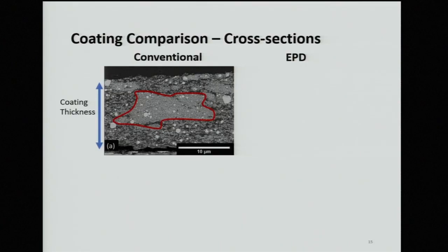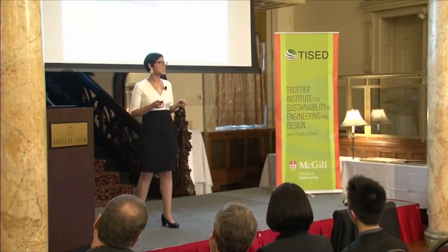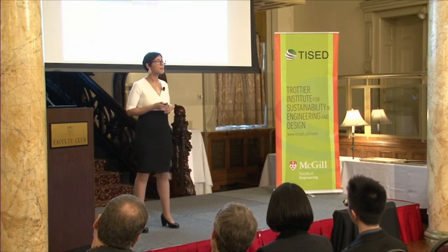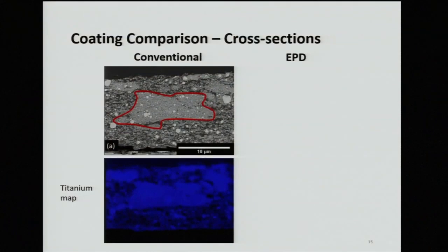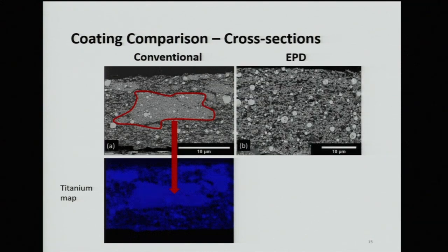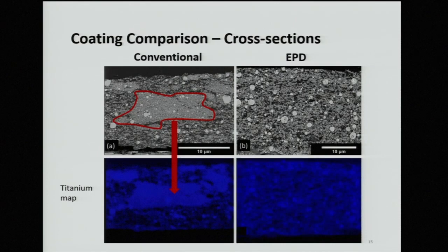With the scanning electron microscope, we can use a technique called energy dispersive spectroscopy, where we can map out elements. Lithium titanate is the only material that has titanium in it. So if we then make a titanium map, we can see where the lithium titanate is spread out. And that's just what we did. So we found out that this gray agglomeration or chunk in the middle is lithium titanate, with the carbon and the binder spread around. Now, if we compare what this looks like with the EPD electrode and its corresponding titanium map, we see a huge difference, right?